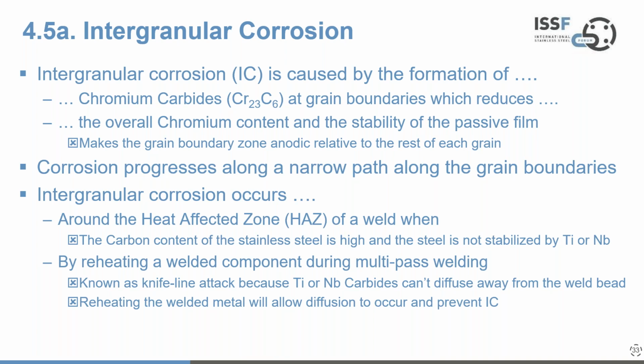And that means that the grain boundary zone where this chromium has been sucked out from becomes anodic relative to the rest of each grain in the structure. And then the corrosion can occur along a narrow path along these grain boundaries. This type of corrosion occurs particularly in situations of welding. So in the heat affected zone around a weld, if the carbon content of the stainless steel is high and/or the steel is not stabilized with titanium or niobium, which will preferentially bond with the carbon at these elevated temperatures, then you will get intergranular corrosion close to the heat affected zone.